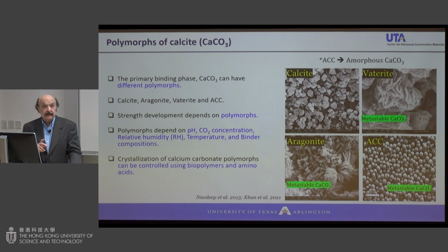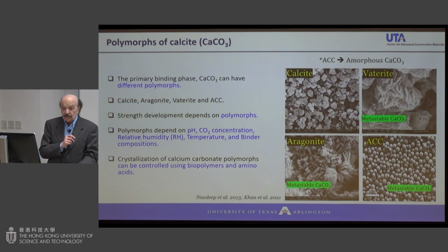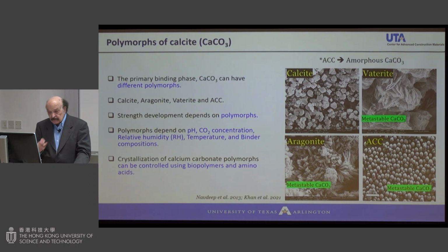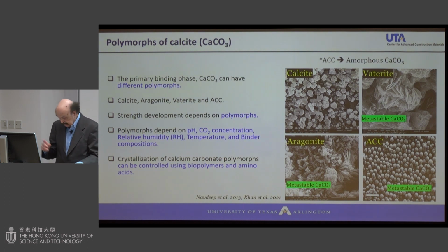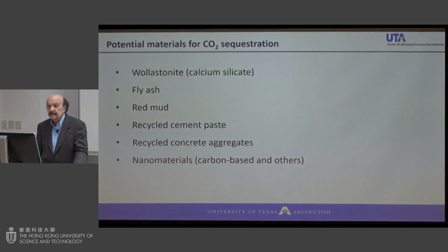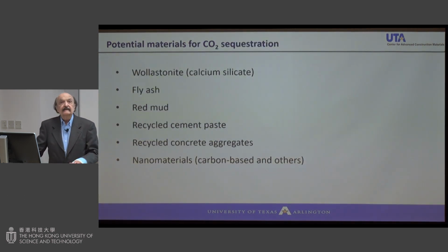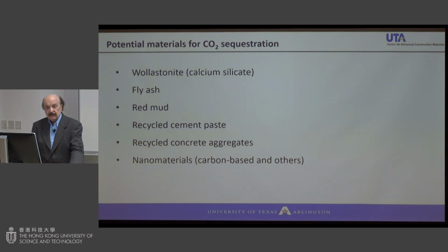One of my colleagues, Varda Ashraf, is adding, for example, a biopolymer to stabilize the amorphous calcium carbonate. A small amount of dopamine and amino acid can stabilize amorphous calcium carbonate and make the materials much stronger. I will show you one slide. So what are the different materials people have tried to help accelerate CO2 sequestration?